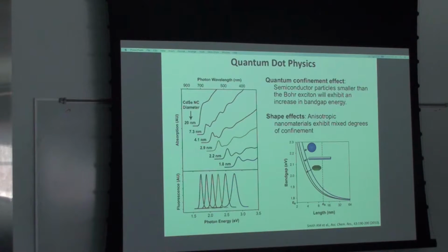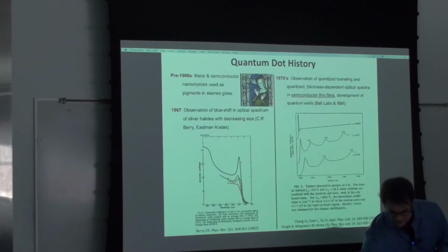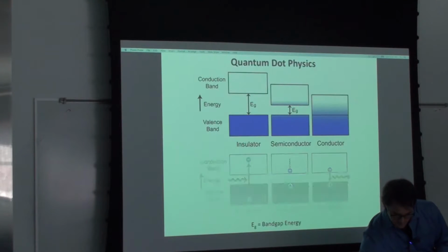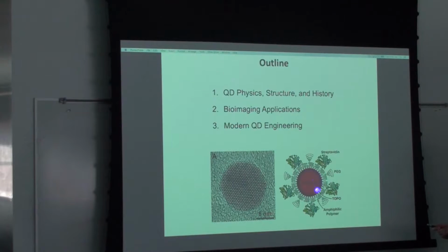That's a good question. This core shell structure is the one example that's most commonly used. They're really broad examples of types of materials that are grown as core shells. And they give you tons and tons of unique properties when you do that. So the classical one of cadmium selenide zinc sulfide is this structure. Basically, that growth of zinc sulfide doesn't really change the color. That's basically because it's just a great insulator. It tunes it by just a couple nanometers, but it really has no major impact.